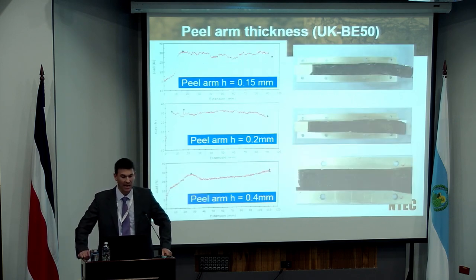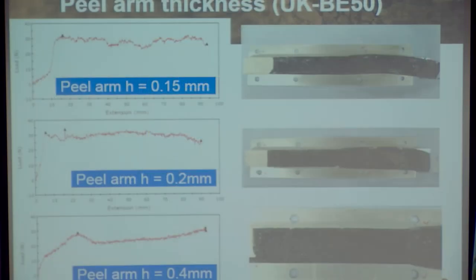And I said we would also play around by changing your aluminium peel arm thickness. So the equations that are used for the peel test are based on a plastic analysis or an elastic analysis, depending on which approach you take. They give very similar results if everything is the same. But one of the factors that influences those analyses is how thick your aluminium peel arm is. And so we looked at three different peel arms, or three different sheets of aluminium: 150 microns, 200 microns, and then a much thicker 400 microns.